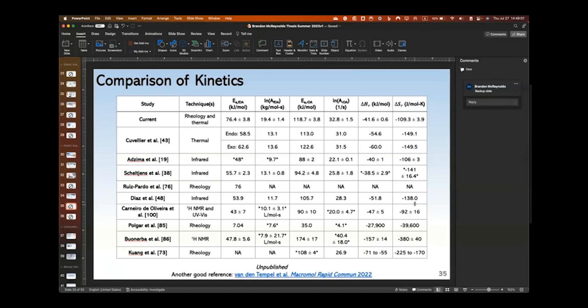So really, 27,900. Yeah, I thought it was very strange as well. But no, it was legitimate. I double checked that. But other values also pretty much offset to all the other literature. So maybe their method could be something different. Yeah, I think in this paper they were studying the rheology, but they were also using an elastomer, so there's very few cross-linking sites. So 4.1 is also pretty much offset. Yeah, so their kinetic parameters were off by a lot too, or not off, but just a lot smaller than you'd expect.